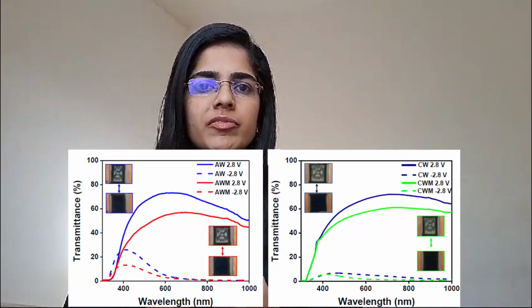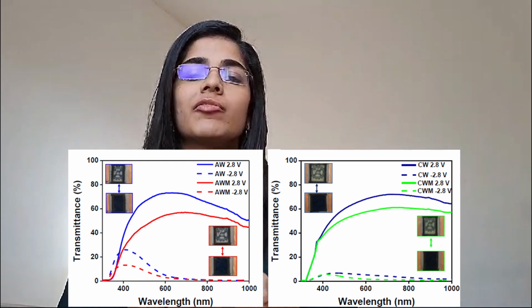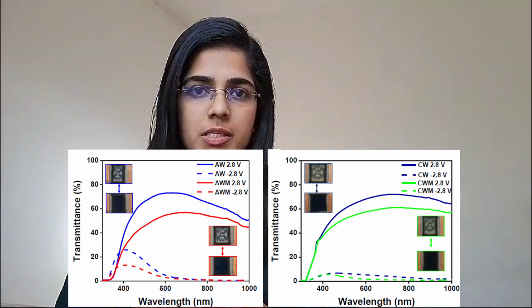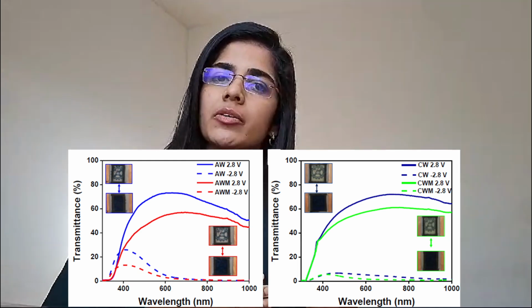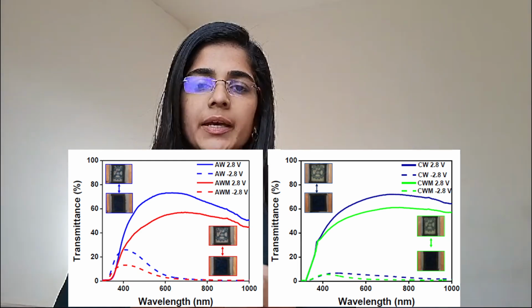In addition, electrochromic performance assessments were conducted on 4 different devices fabricated with the designed electrodes. MnO2 overcoating improved the coloration efficiency of the electrochromic devices for both amorphous and crystalline phases, with the amorphous phase displaying greater coloration efficiency. A lower coloration efficiency value means more stored charges are required for the same change in optical density, thereby making the crystalline phase better for simultaneous electrochromic as well as charge storage performances.